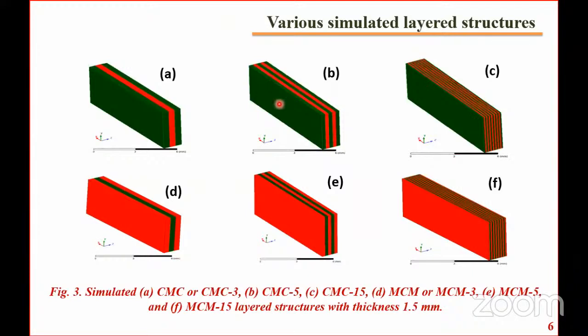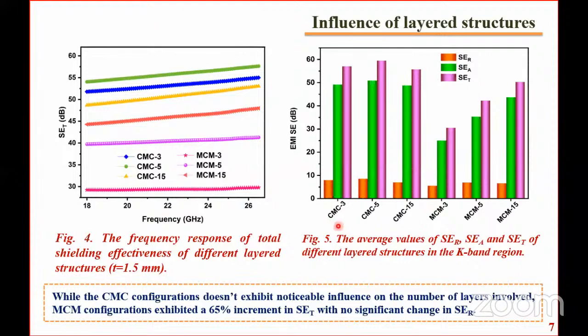We have also simulated various layered structures within the same thickness, and as the number of layers is increased from 3 to 15, let's see what happens. From this, it is clear that as the number of layers increases in the CMC structures, there is no particular variation in the total shielding effectiveness. It is already in the range between 55 and 60. In the MCM structures, it is very interesting to note that as the number of layers increases from 3 to 15, the total shielding effectiveness is increased from around 30 to 50 dB.